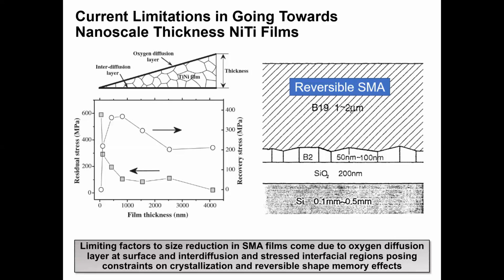And this is another focus area of this dissertation, namely reducing processing temperatures to, 1, limit the interfacial diffusion, and 2, enable lower temperature processing of SMA onto CMOS and polymer materials, which is currently limited by the high temperature processing steps required to crystallize the SMA films.